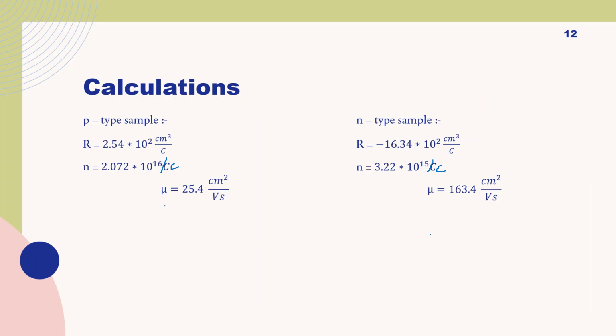So here are the calculated values for p-type and n-type germanium samples. We can see that these values are very close to the theoretical values. Specifically, the values of charge carrier density are easier to look at, and we can see that those are very close to the range of theoretical values.